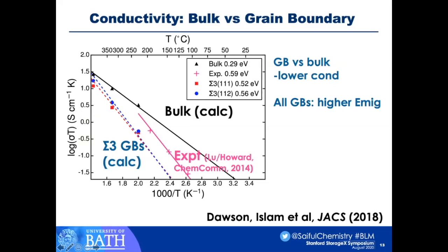This is some work that we published in JACS a couple of years ago. We've shown for the first time in this anti-perovskite some quantitative atomistic insights into the grain boundary resistance and the migration barriers. It helps to explain why the calculated DFT values were lower than experimental, if you just consider the bulk migration without considering the grain boundary resistance as well. We've extended this work to some sulfides, though I won't have time to talk about it, where we find much, much lower grain boundary resistance. The sulfides tend to be quite different from the oxides in terms of grain boundaries.